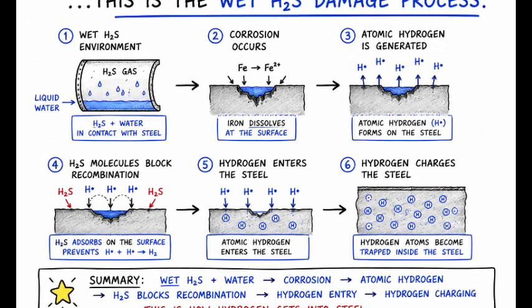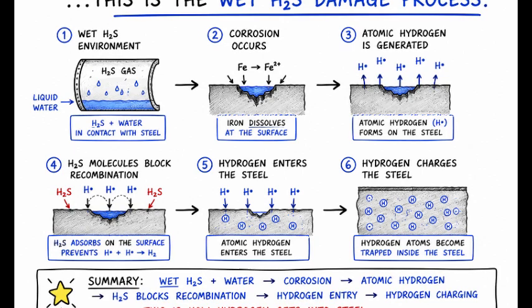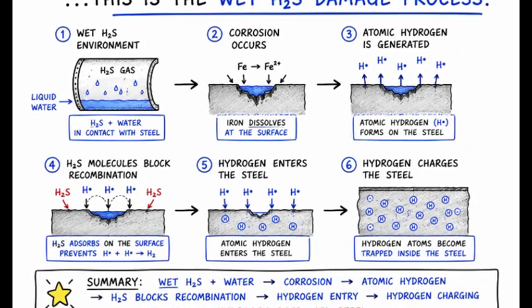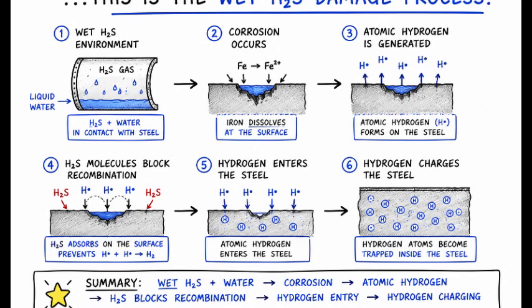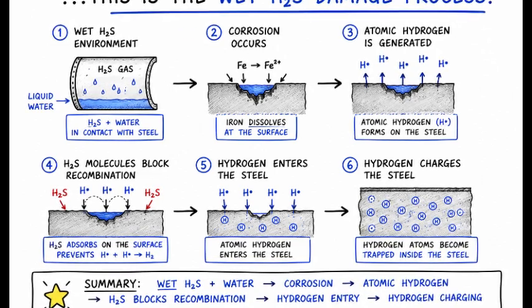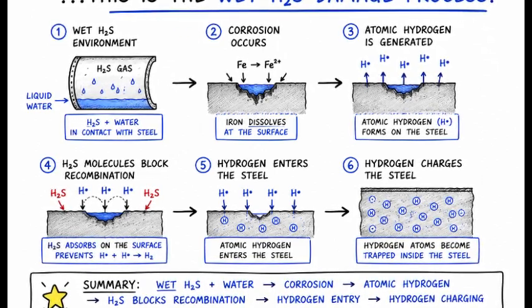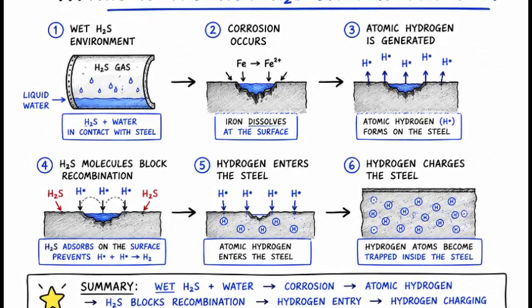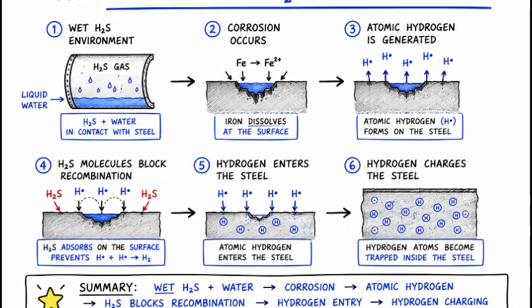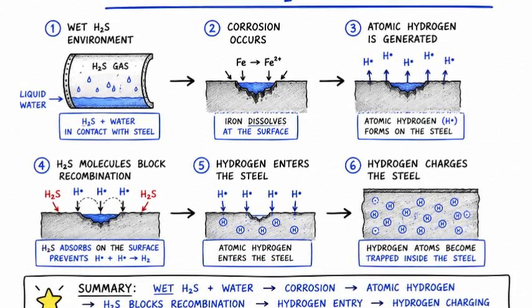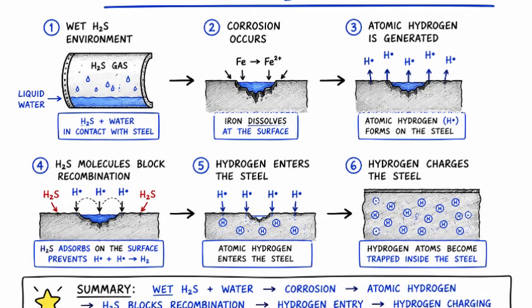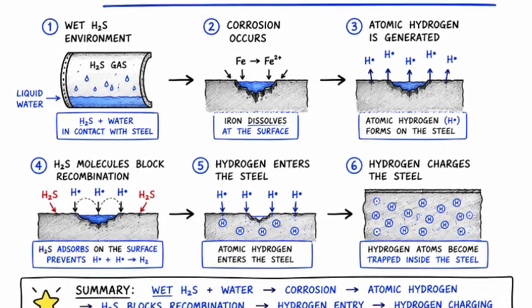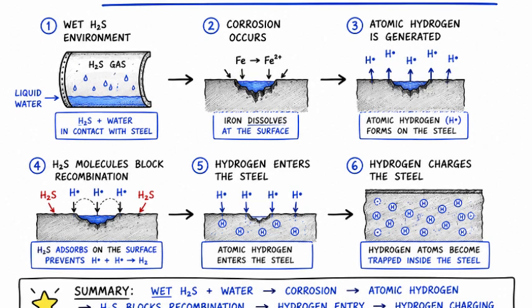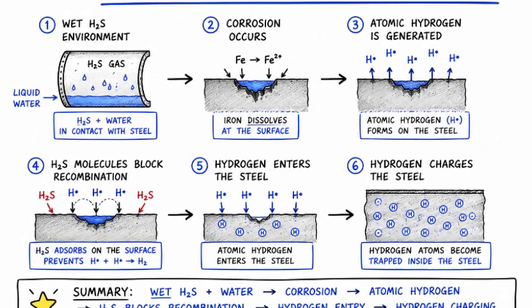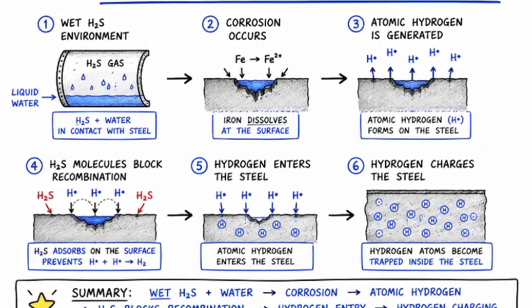Instead of allowing atomic hydrogen to combine and leave the surface, sulfur adsorbs to the metal surface, blocking hydrogen atoms from active catalytic sites that would normally promote hydrogen gas formation. As a result, more hydrogen atoms are forced to enter the steel. Less hydrogen gas escapes, and hydrogen begins diffusing through the metal. This absorption process is known as hydrogen charging. The severity of hydrogen charging controls the likelihood of wet H2S damage.